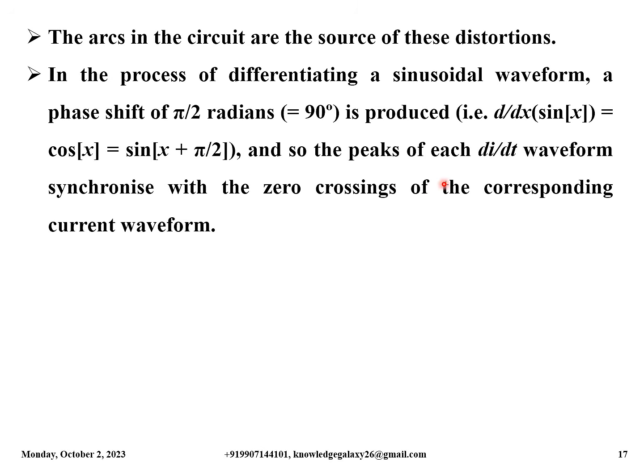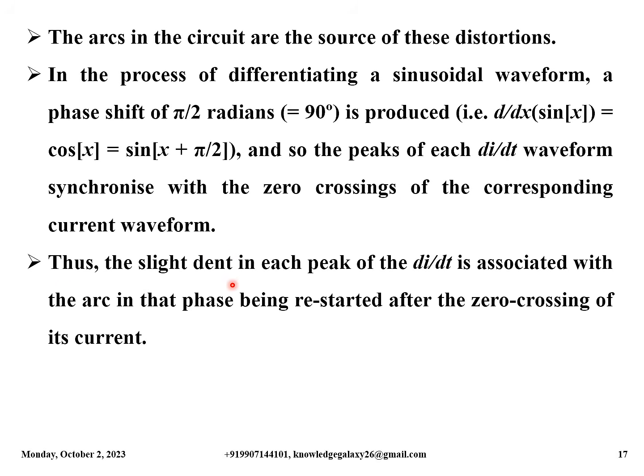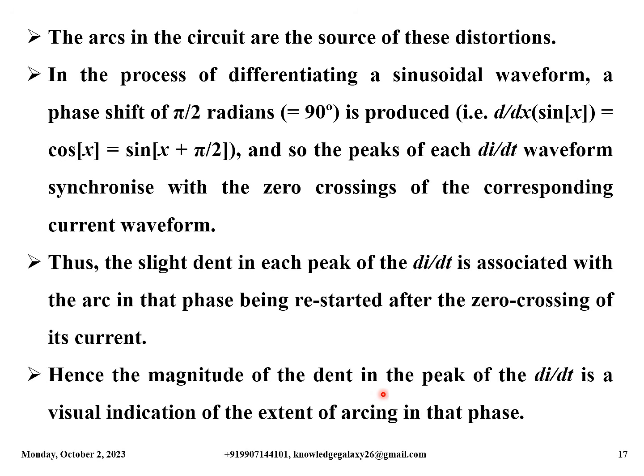And so the peaks of each di/dt waveform synchronize with the zero crossings of the corresponding current waveform. Thus, the slight dent in each peak of the di/dt is associated with the arc in that phase being restarted after the zero crossing of its current. Hence, the magnitude of the dent in the peak of the di/dt is a visual indication of the extent of arcing in that phase.